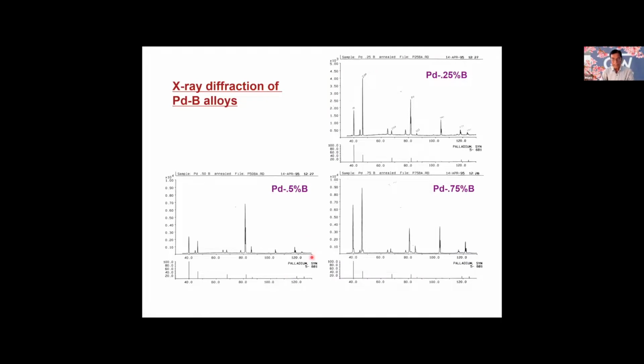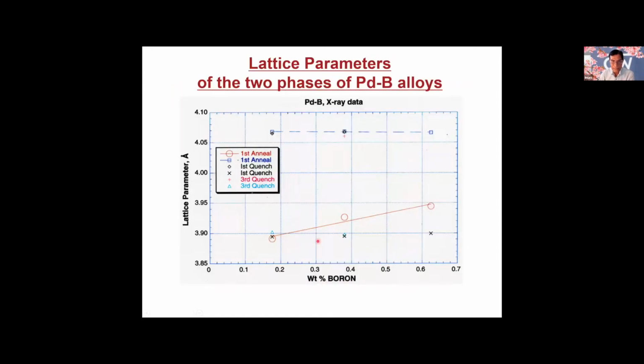So here is some X-ray work. This is a 0.25 boron content. This is the pure palladium, here is the 0.5, and here is the 0.75. This gives you an indication that we have two phases, and here is the indication. You can see this is the matrix lattice parameter. We are talking about weight percent of boron on the x-axis, and this is the other phase which is coming on. As you increase the boron content, the other phase, which is a smaller phase, its lattice parameter increases, and this is the matrix one here.